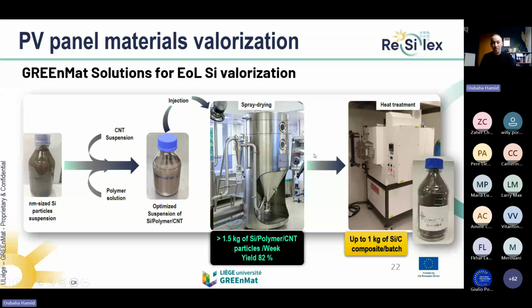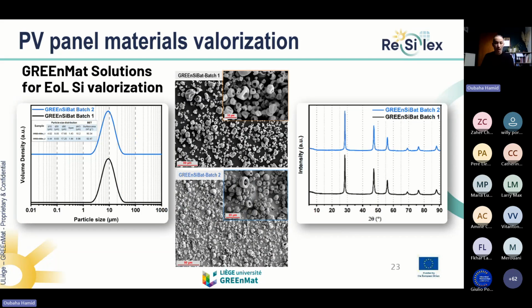Then the obtained secondary particles are heat treated to obtain the final silicon carbon composite. And now with Resilex support we are reaching 1 kilogram of this composite per batch. And to assess the stability of our process, we produced different batches, and here I show the comparison between two batches. You can see that the physicochemical properties of our silicon are quite similar, attesting the good stability of our process.